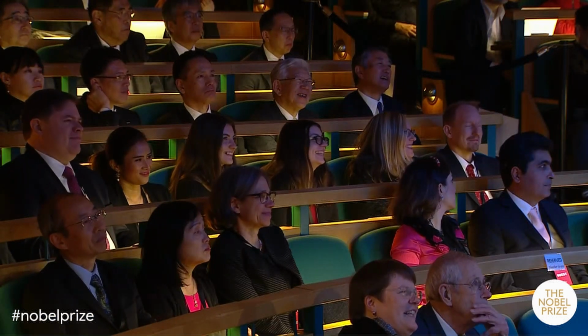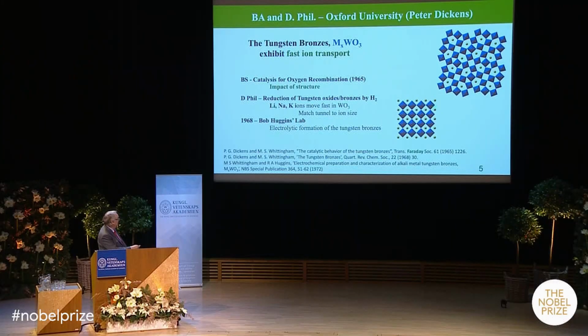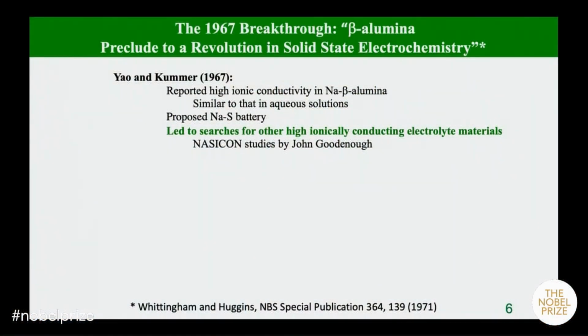So we studied the transport behavior in these materials, and then when I went to Bob Huggins' lab, we actually did the thermodynamic behavior of how we synthesize these materials using electrochemical means. But there was a significant breakthrough. I went in '68. The previous year, researchers at the Ford Motor Company had discovered the fast ion transport in sodium beta alumina, showed that sodium ions in this material move just as fast as sodium ions in water.